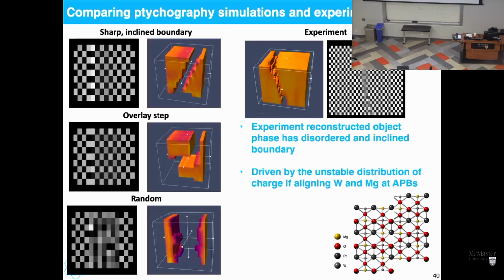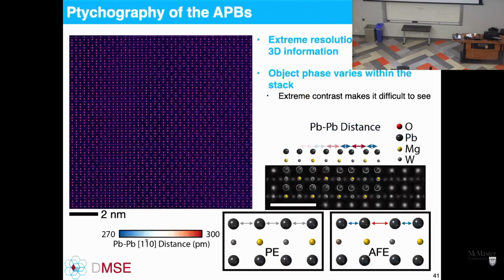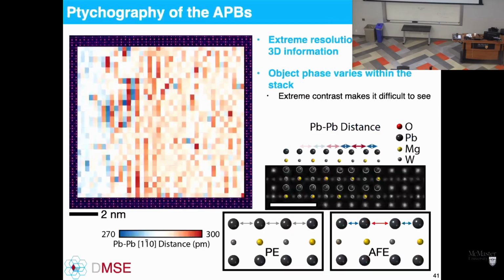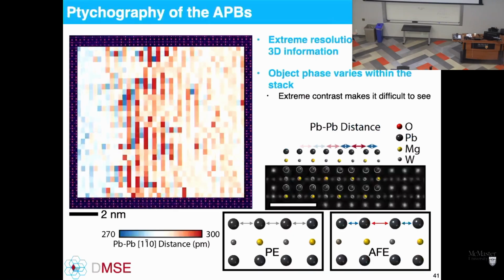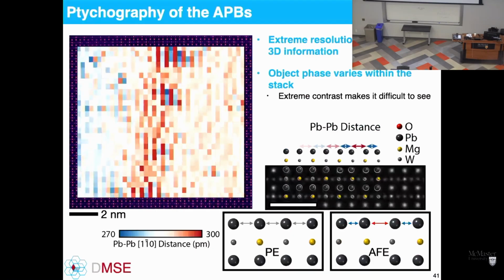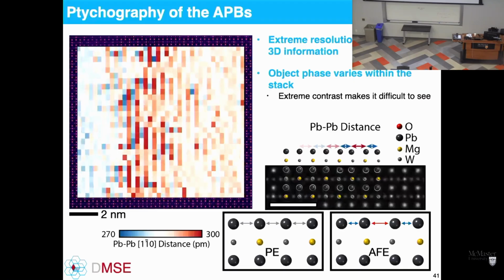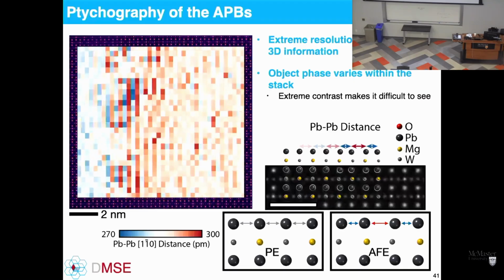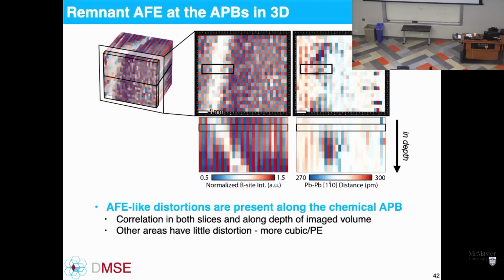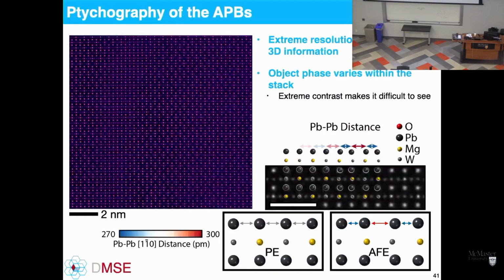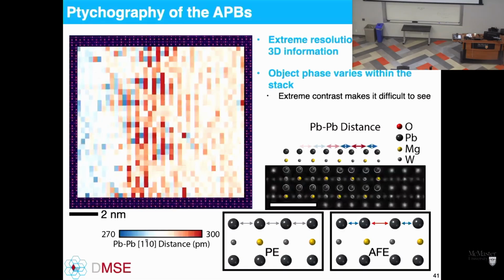The boundary is much narrower than that blurring or that image intensity would suggest. This is driven by, again, that unstable alignment of tungsten next to each other. We can also measure antiferroelectric distortions across here. If we measure the lead-lead distances across here, you see this ordering of red, blue, red, blue, red, blue across here. This is due to the antiferroelectric structure of lead magnesium tungstate compared to the paraelectric where they're just equal. And again, it marches from left to right.